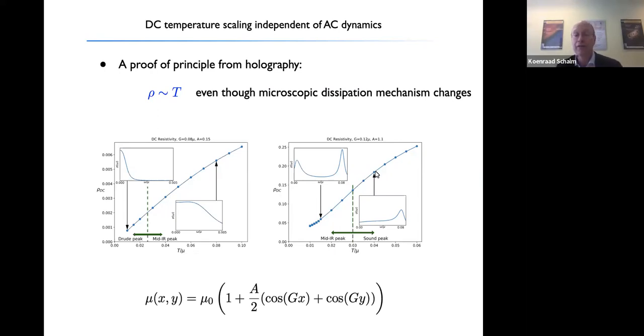So this is a holographic system, which is based on the so-called Gubser-Rocha black hole. But the key part is that this is a holographic system where we have put the holographic strange metal in a background lattice. So the key ingredient in this system is that we've made a lattice which communicates with the strange metal through a modulated chemical potential, which has an average, and then there is a cosine wave in the X direction and a cosine undulation in the Y direction.